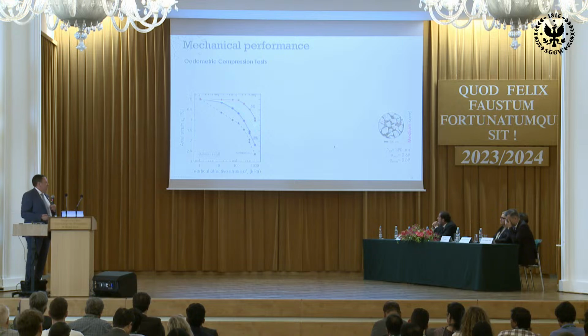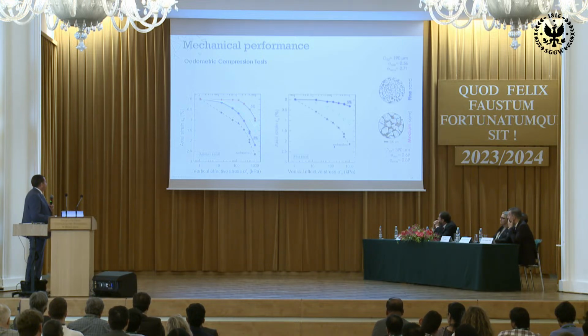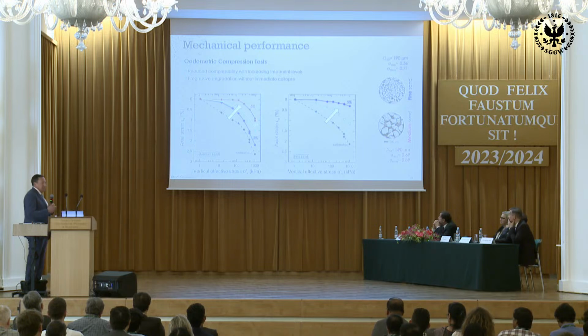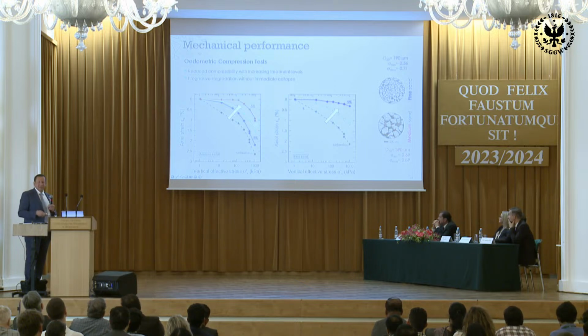We did several oedometric tests on different types of sands at different amounts of calcite precipitation to understand what's happening. Basically, what we see is a stiffer material, so the slope is stiffer, and a pre-consolidation stress that is decreasing, like we are plastifying the material.